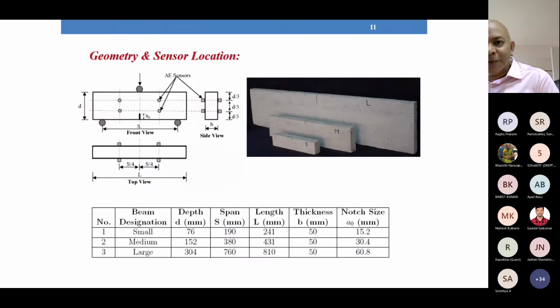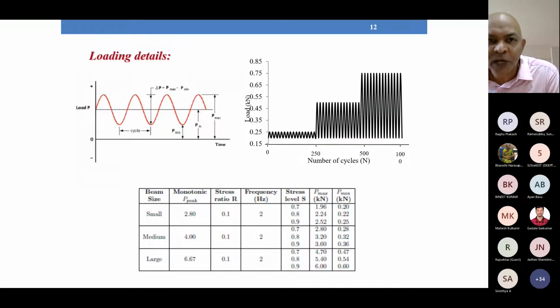Here, let me explain the 3-point bend specimen. These are 3 different sizes of notched beams, which we call small, medium, and large, and they are geometrically similar, meaning the notch-to-depth ratio is constant for all 3, and the span-to-depth ratio is also constant. The large specimen is approximately 0.8 meters, less than a meter. The medium beam is 0.4 meters and the small specimen is 0.25 meters. The thicknesses are constant at 50 mm, and there is a notch provided. We have used acoustic emission sensors, and I will show you the acoustic emission sensors and all the instrumentation later on.